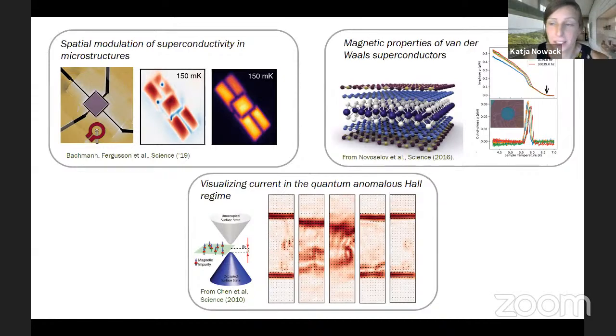So there is something I didn't talk about at all, which is when we tune outside of the quantized plateau, meaning when sigma XX really comes up again, we actually see very strong signals. If we take those signals at face value and interpret them as currents, it's on the overview slide. I think you're thinking about these kinds of signals. These images were actually taken outside of the quantized plateau, and we see a lot of higher harmonics and nonlinear signals in that regime.